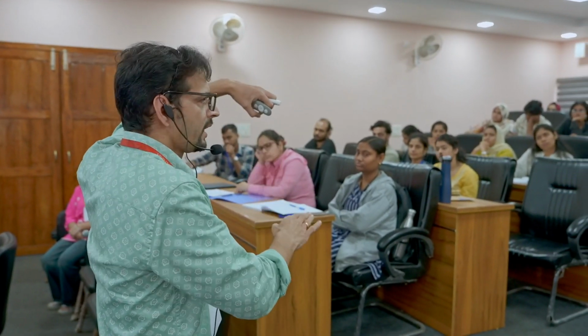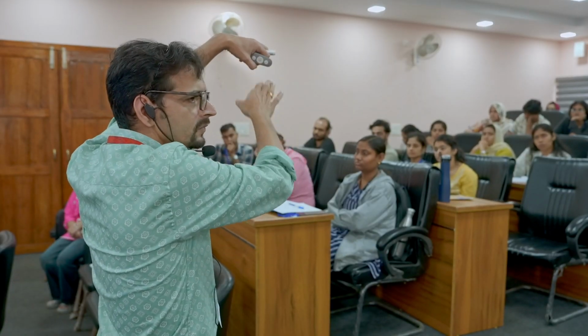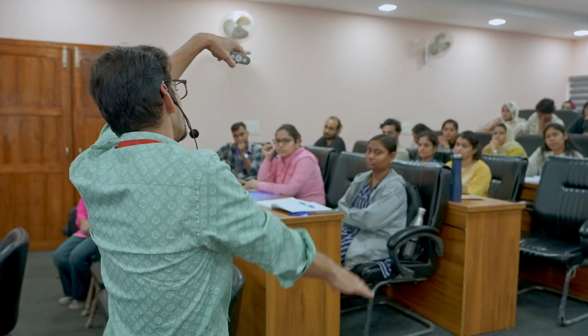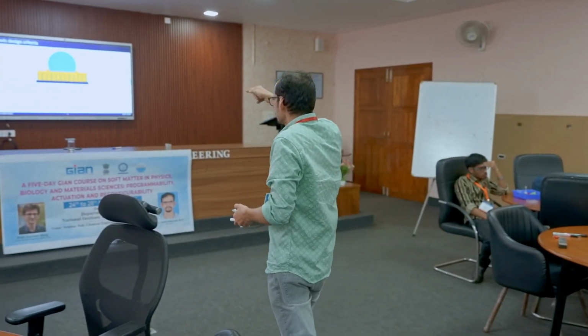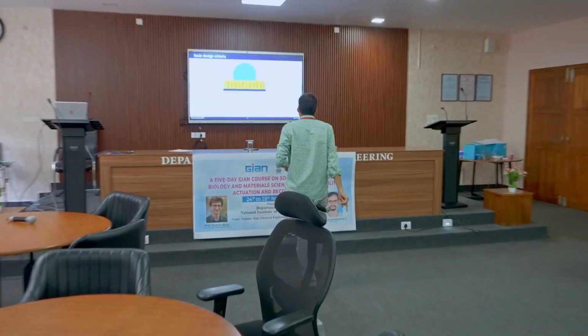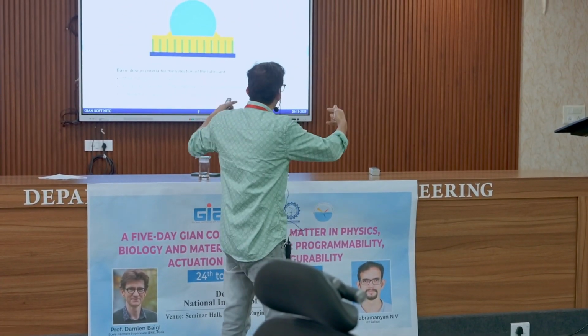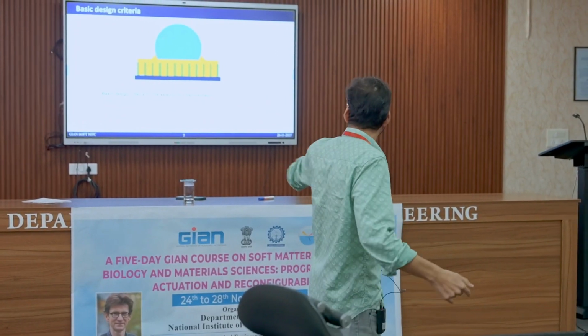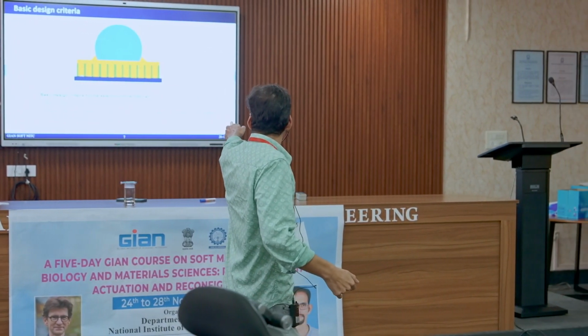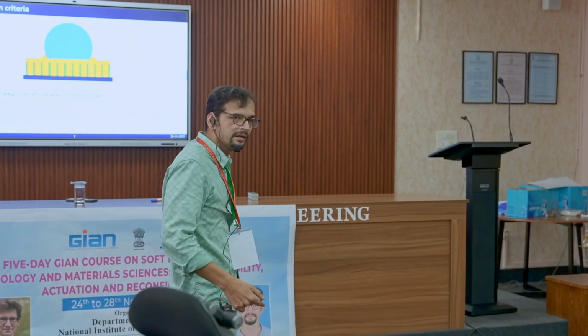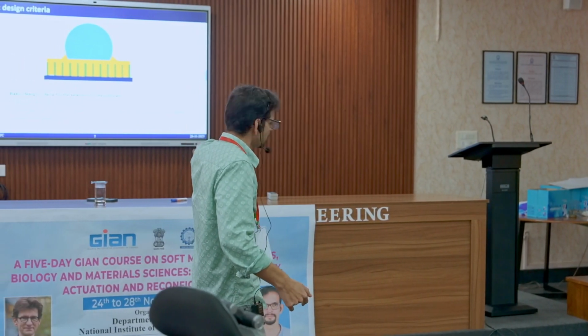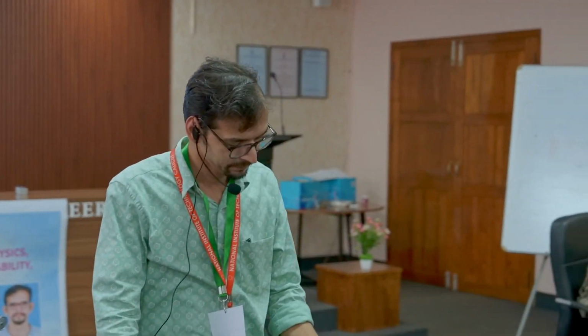Once it goes there, since it's wetting, it will stay there, and then you can keep it at a tilted angle for a long time, so that the excess layers will be removed. Still there will be a monolayer, and the liquid inside the pores will remain there. Then you can see a yellow region which was not there in the previous case, right? The Cassie and Wenzel states, right? This is because they are immiscible, and the lubricant has a stronger ability to wet the textured solid surface than the liquid to be repelled. We mentioned that, right? Then lubricant and liquid must be immiscible. Some conditions need to be satisfied always.